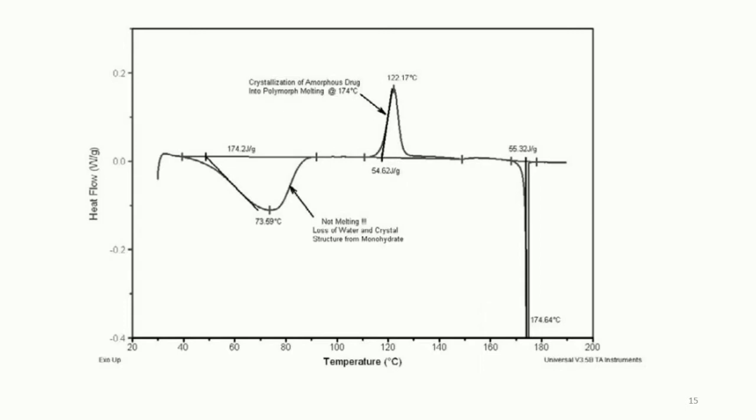This diagram represents a particular drug that has one water of crystallization — a monohydrated drug. This temperature range depicts the endothermic peak of water vaporization from the pinhole pan, due to the removal of hydration from the drug. For this material, which is about 99.9% crystalline according to X-ray diffraction results, the crystal structure is also lost when the water evaporates.